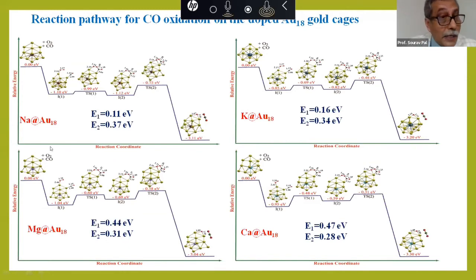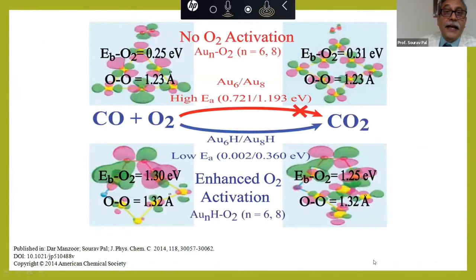So again, our message is that if we can put on this gold Au18 cage sodium, these metals, and I believe some of them would be easy to do, like magnesium, calcium. I'm not very sure about sodium and potassium in terms of synthesis. This will actually help the CO oxidation reaction. So as you can see, we have actually done a complete reaction mechanism and looked at all the intermediates and transition states.